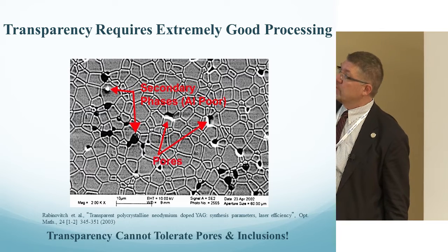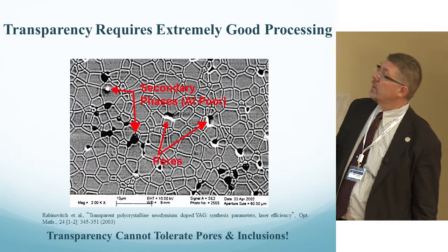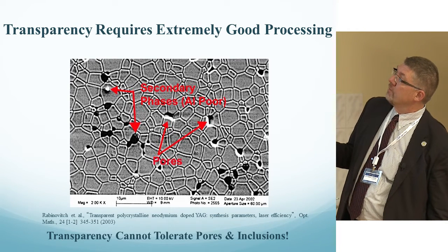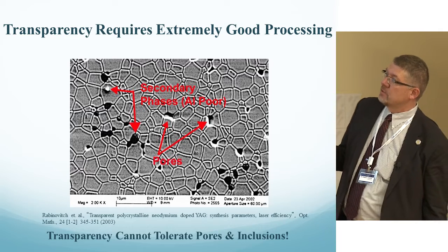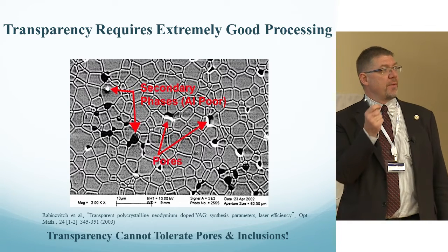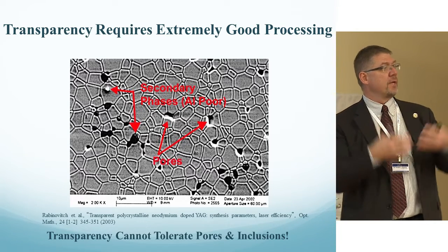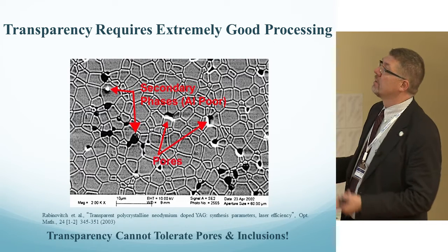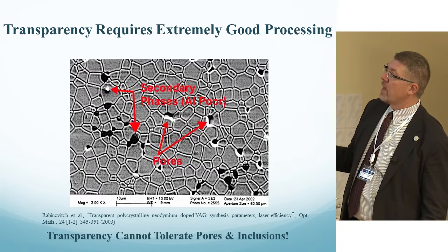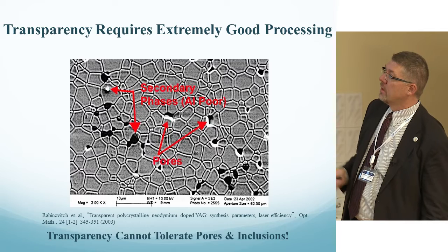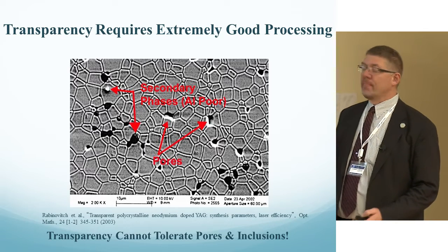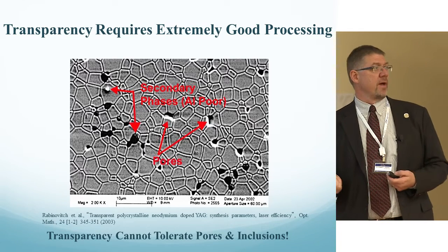The processing of those powders is critical. If you look here, you've got these secondary phases. These are the black dots that you see, regions where there wasn't enough aluminum in the mix to get it all to come in single phase. And then you've got these pores that are lined up on these very white portions of the grain boundaries. This isn't tolerable in the manufacturing process.